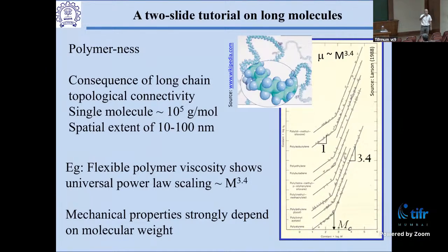Because this tells you why the molecular weight is so important. If I take a chain and I break it by a factor of 2, I cut it, my average molecular weight goes down by a factor of 2, my viscosity goes down by a factor of 10. It becomes that much less useful. So the molecular weight is an extremely important attribute for the polymer, and preserving that molecular weight is important in terms of the applications of this material. And so mechanical properties depend on that.